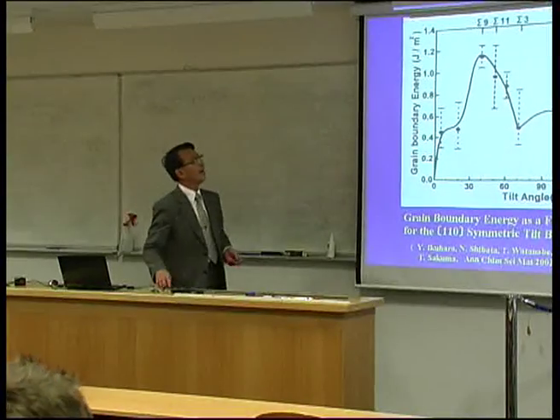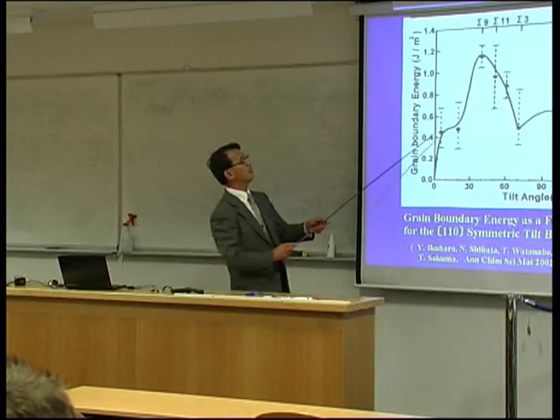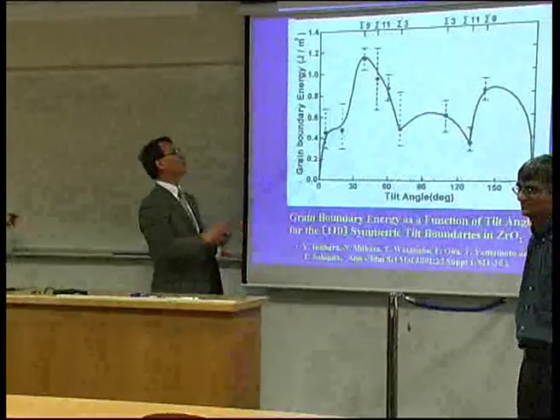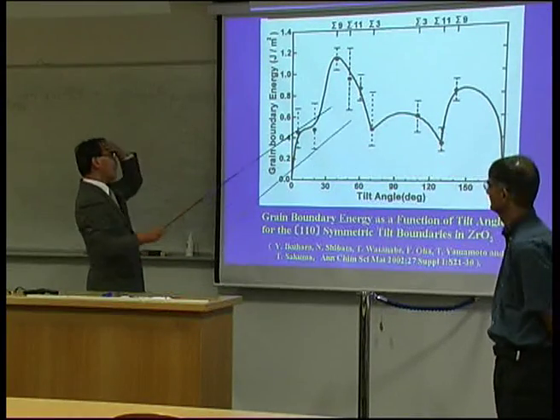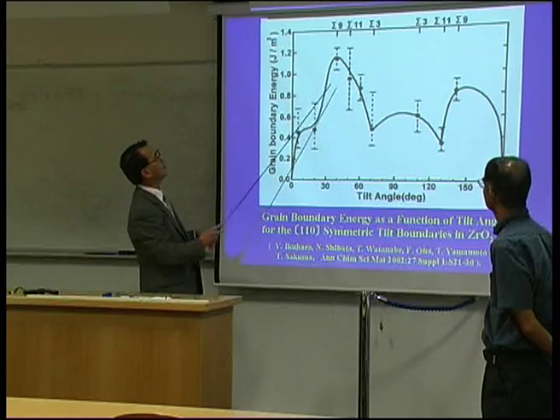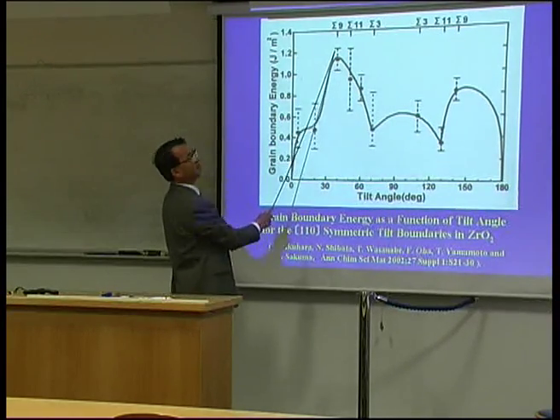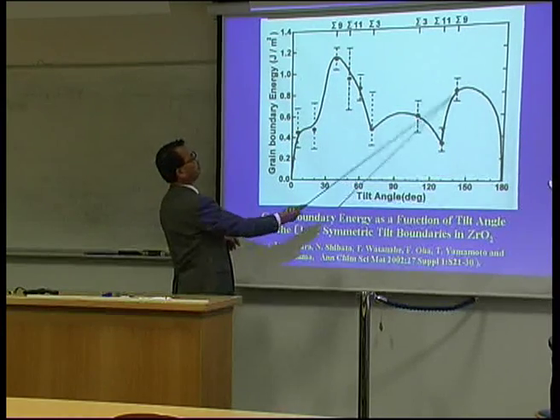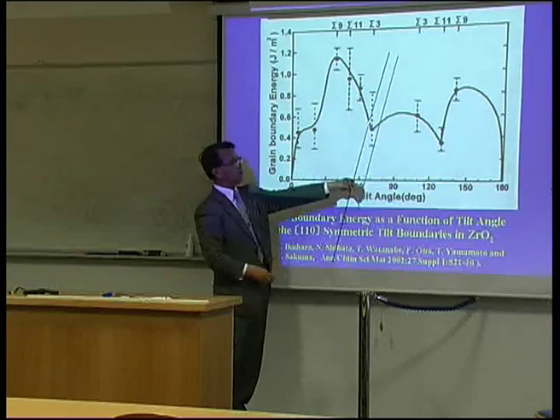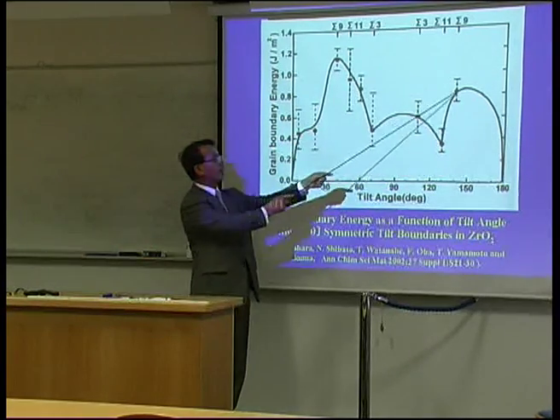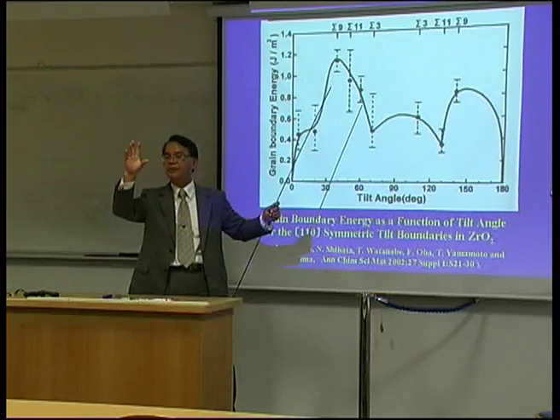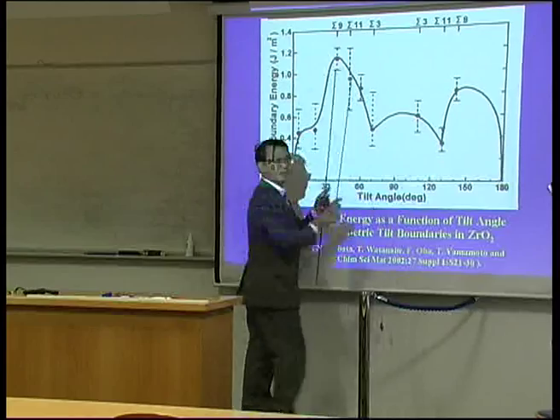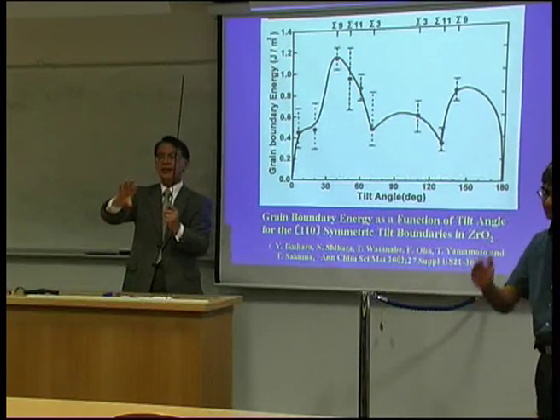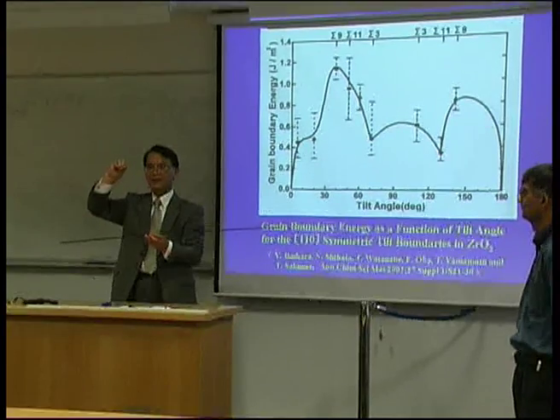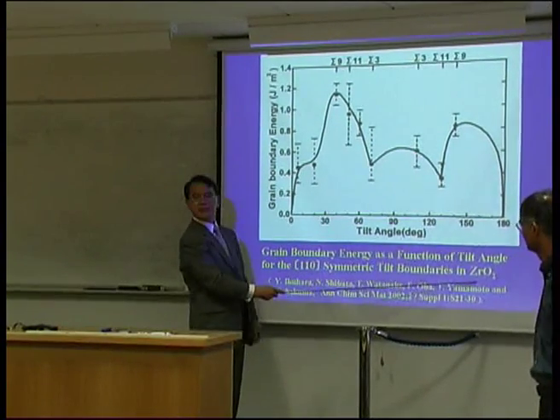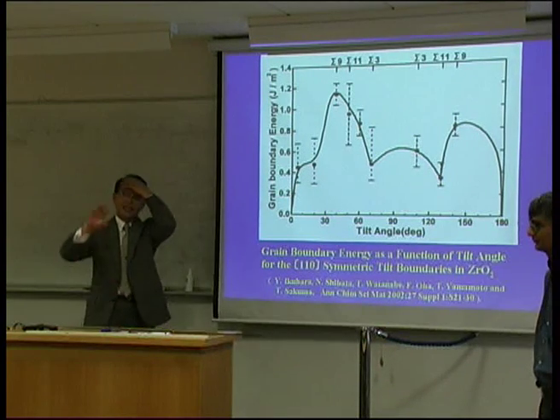The solid line in this graph, is this actually a theory or is it just a trace? I think it is also a trace, not theoretical. But we had better look at it carefully, because even for the same sigma relative orientation, the value is different. You have to take into account the grain boundary plane, the crystallography also, because depending on the inclination it is a different boundary, so the atomistic configuration is different. In the case of ceramics, the electronic state, or charge, is different.